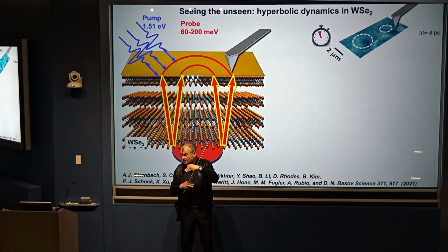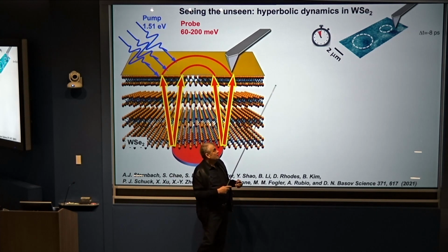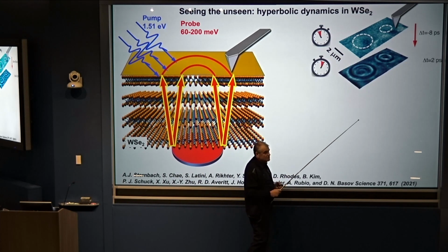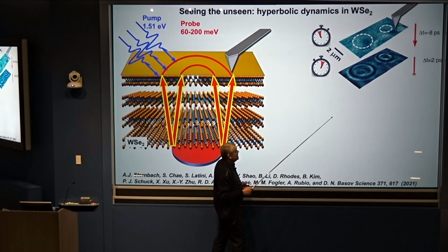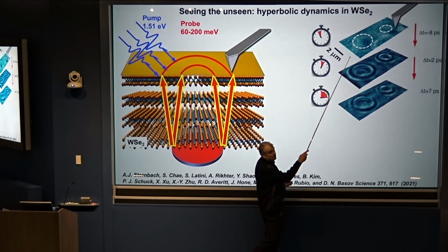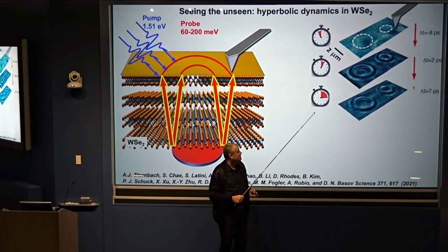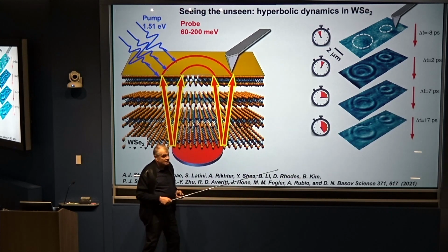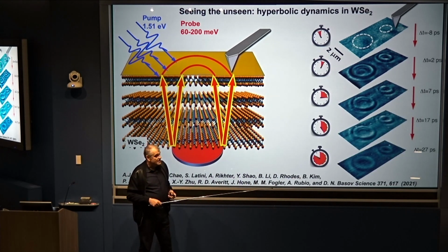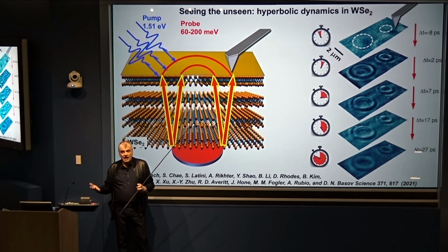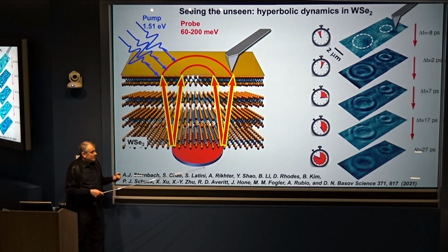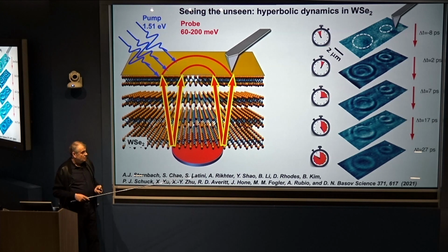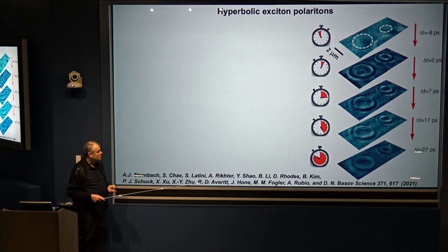But the crystal is thick enough so that we don't reach it with nanolight in the absence of waveguiding. Then the pump pulse arrives. It transformed tungsten selenide into a new electronic state supporting hyperbolic waves. And now we do see these two rims surrounding these golden antennas. This effect is short-lived, at least it lives only for maybe several tens of picoseconds. That's the time over which this exotic electronic state exists. Then it dies off. But as far as I know, this is the first demonstration of hyperbolicity.